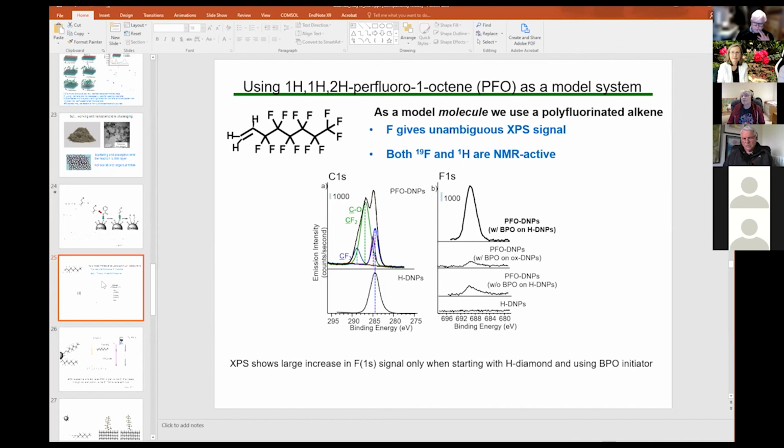Yeah, I would say effectively all of these will give something which is on the order of a few times 10 to the 14 molecules per square centimeter. If you estimate the size of an alkyl chain, and we actually published at one point a molecular dynamics simulation, if you just assume molecules randomly land and some sites are occluded, you get to something called the jamming limit. And the jamming limit is something like 3/4 of the maximum packing density of molecules. So in general, that turns out to be on the order of a few times 10 to the 14. If you've got a bigger molecule, it might be on the order of 10 to the 13.